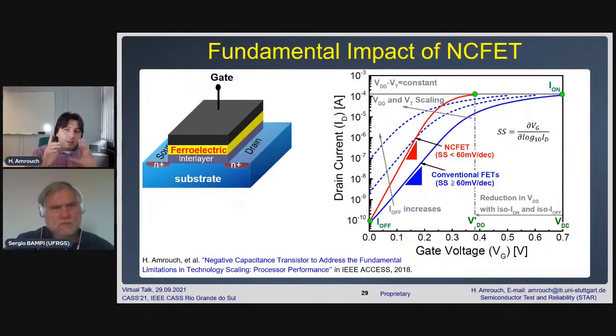The on current is doing well. Hysteresis free is very challenging. Having a very thin ferroelectric layer is not easy. And nowadays there are lots of investigations not in NCFET but in ferroelectric devices for memory. So this is a very active topic I did not talk about. But also nowadays, even for logic, they talk about having a better high-K layer, high-K gate, not necessarily to have the negative capacitor effect, but at least a better high-K to have a better capacitor and better electrostatic integrity.